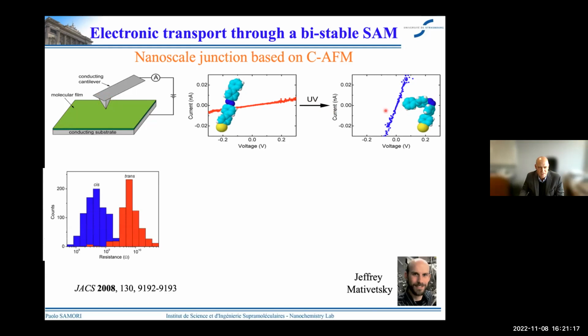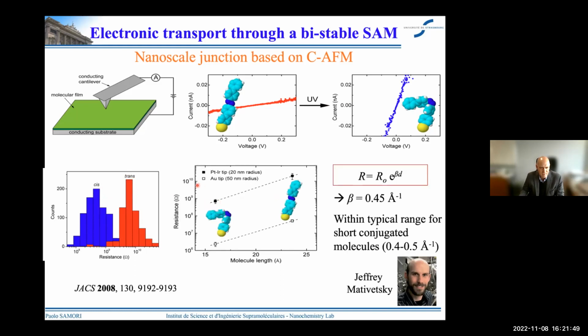And so, of course, when you do scanning probe techniques or local probe techniques, never trust a single measurement. You have to do statistics, which demonstrate indeed that the average resistance of our self-assembled monolayer is lower when you have a thinner monolayer covering the gold electrode, whereas when this layer is thicker, due to the fact that we have to tunnel through a thicker barrier, the resistance is higher. You can plot the resistance as a function of molecular length, and despite having only two data points, we can determine beta, the transmission factor of tunneling, which turns out to be about 0.45 angstrom^-1, in good agreement with the typical values of beta for conjugated small molecules. That was work done by Jeffrey Mativetsky in our group when he was working as a postdoc.